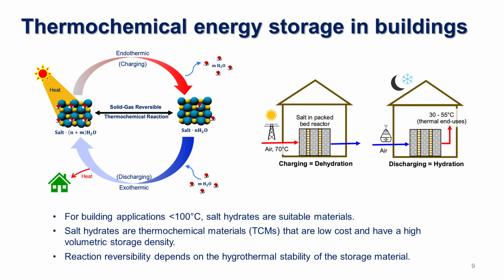And so these salt hydrates that we work with are suitable for temperatures under 100 degrees Celsius, because we're working in the building space. They're very low cost, so very common salts like calcium chloride is a thermochemical material. And they have these inherently high storage densities because, again, you're extracting the energy associated with these chemical bonds. The challenge, however, is in theory, yes, this is a nice reversible solid gas reaction, but in reality, that reaction reversibility really depends on the stability of the storage material. And so this is where there are a number of challenges that we're trying to address.